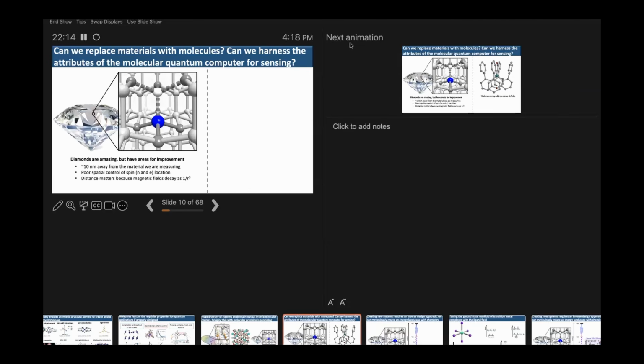It exists because the way De Beers makes diamonds is they take a diamond and they shoot ions at it, and we are not under thermodynamic control here, right? This is a kinetic species that we isolate. Put it in the diamond, and then once it's there, if we were to move it over, we create exactly the same thing. So there's no driving force thermodynamically to move it, and the barrier to moving it is breaking a carbon-carbon bond. And so this thing persists once we create it, but if there's any chemical way for it to dissipate, it'll dissipate. And that's also why it has to be buried deep within the surface of the diamond.